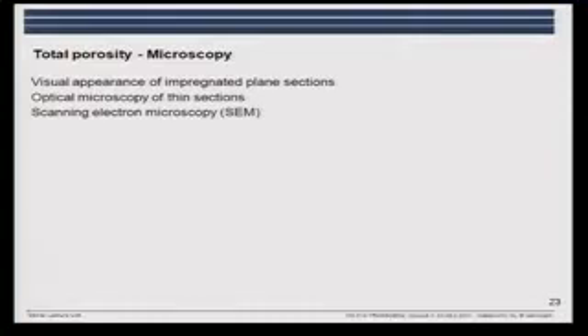And if we use microscopy, we can look at different levels. We can have visual appearance of impregnated plane sections, large sections, optical microscopy of the thin sections, and then the scanning electron microscopy. And we can even go further down. So this is a plane section. That's a core which has been drilled out, and you can see it looks horrible. It is actually a core where we've had alkali silica reactions, and there's extensive cracking parallel to the surface.